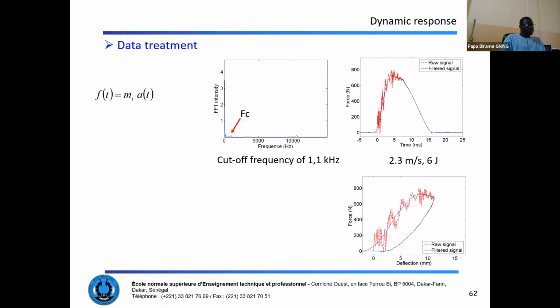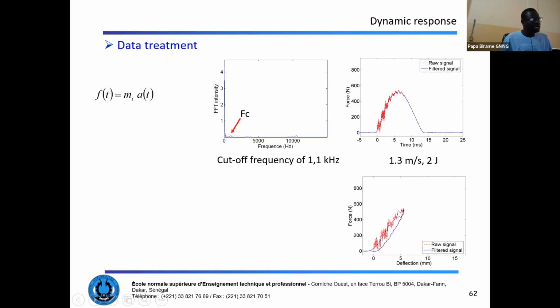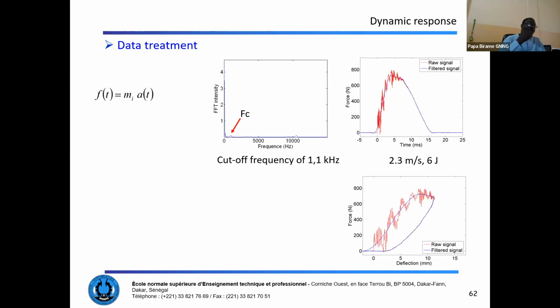So when the impact has low speed and low incident energy, you have a loading path which differs from the unloading path, and the area inside the loading and unloading represents the dissipated energy, which is quite small at small impacting energy. So when you increase the incident energy, the duration of the impact is increased, and also the maximum force is increased. At the same time, you have an increase of the dissipated energy, which creates damage inside the specimen.